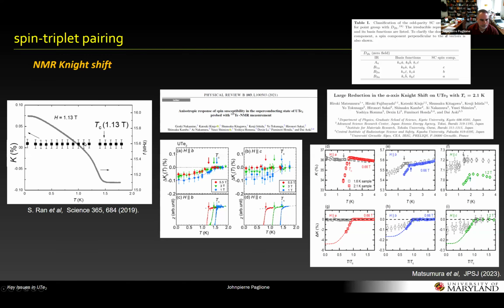This is real data. And then there have been some more refined measurements as we go along, and the most recent data that I've seen, at least from the Aoki group, shows that there is a change in the Knight shift that amounts to a few percent change. And they claim to see it in all three directions. I don't want to be skeptical here, but I would just say that Knight shift NMR is a surface sensitive measurement. It's an RF measurement, and so you have to wonder, given claims of surface phases and so on, how does that affect the interpretation of this data? And furthermore, measuring NMR in a superconductor is a long known challenge.